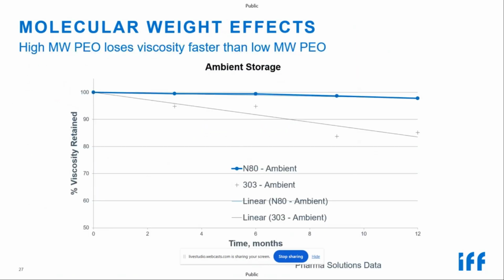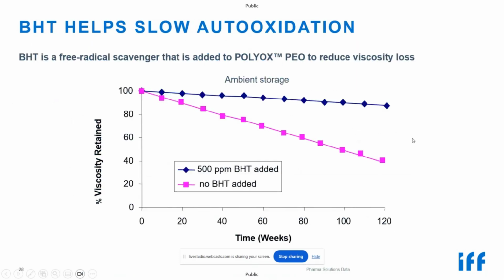All right. I mentioned again the molecular weight impact of auto-oxidation. Higher molecular weight has observed faster viscosity degradation over time. Here I'm showing a low molecular weight, N80, 200,000 molecular weight, in this blue line. This is stored at ambient conditions for up to 12 months. You can see a slow decrease in the observed viscosity over that time. In comparison, for one of our highest molecular weights, 303, 7 million dalton, we see a more rapid decrease in viscosity over that same 12 months.